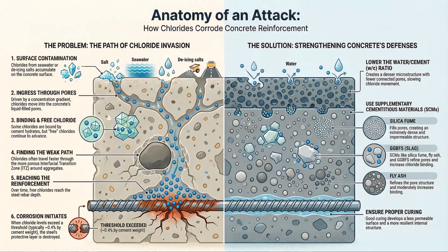So what does this translate to in terms of service life? Because that's the ultimate payoff for the complexity and cost of these materials. The service life reality is the entire reason for these stringent specifications. Without SCMs, reinforcement steel hits that chloride threshold and serious corrosion begins in a shocking 10 to 25 years. Which is just not acceptable for public infrastructure.